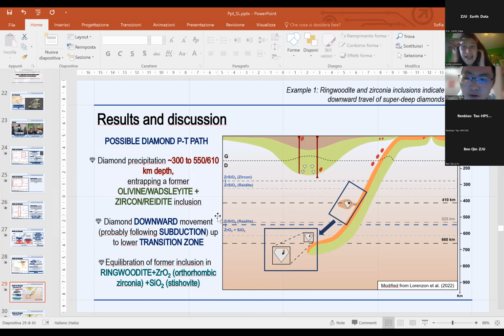And from the carbon and nitrogen isotopic composition, we obtain that the nitrogen content present in the diamond is extremely low. And as I said in my presentation, we suppose that this diamond is a super deep diamond, because in general super deep diamonds do not contain nitrogen, or the amount is extremely low, whereas lithospheric diamonds contain a huge amount of nitrogen, in the order of hundreds of ppm. And for these reasons, we say, okay, probably our diamond is a super deep diamond.